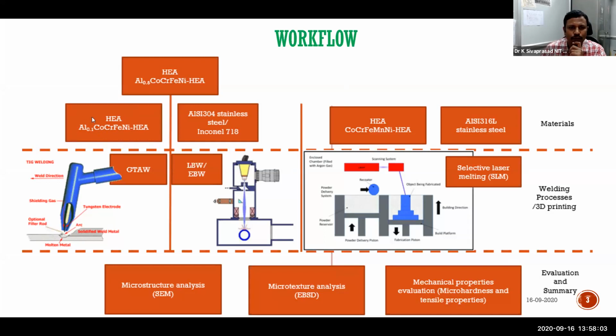So aluminum 0.1 is a single phase FCC, which is similar to austenitic stainless steel or Inconel 718 equivalent. Aluminum 0.5 has some amount of BCC and some amount of HCP fraction. Initially we studied a similar system on this one. Then we felt that weldability is there, but it is somewhat difficult, especially when going for a dissimilar welding system.